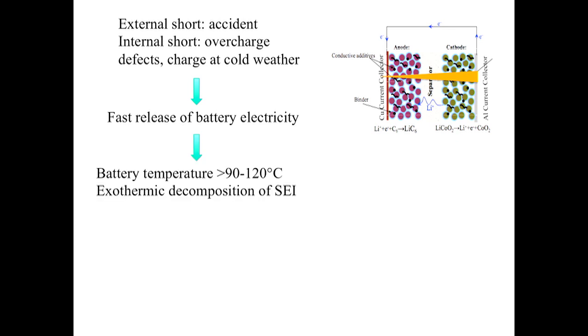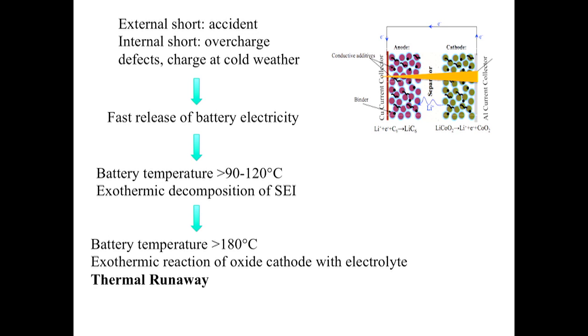When you heat up to roughly 90 to 120 degrees C, the solid electrolyte interface on each of these particle surfaces will self-decompose. It's not stable at that temperature. It's an exothermic reaction, releasing more heat. At this moment, still not catching fire yet. But once it goes up to roughly 180 degrees C, now this is something you don't want your battery to go to. This is the oxide. This lithium cobalt oxide carries a lot of oxygen and will react with the organic electrolyte like crazy. And then this goes through thermal runaway. You don't have control anymore.